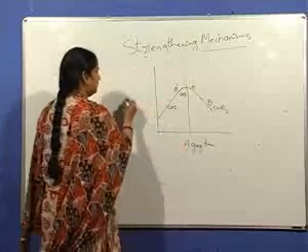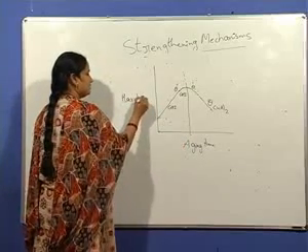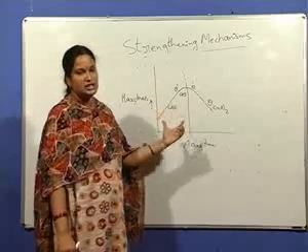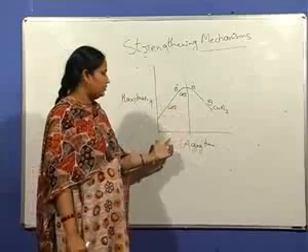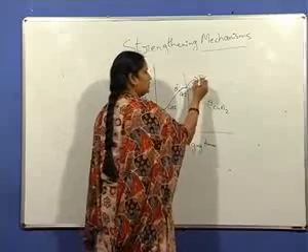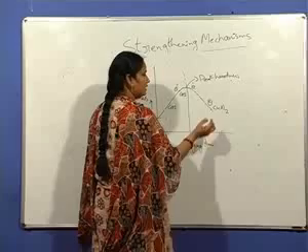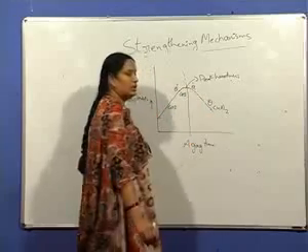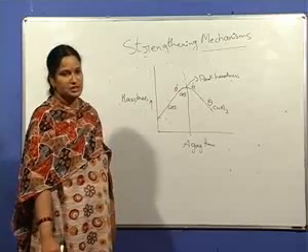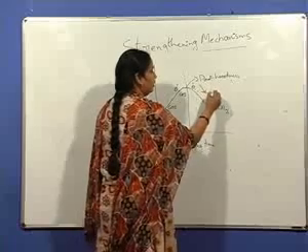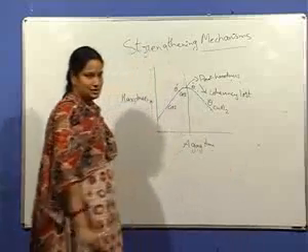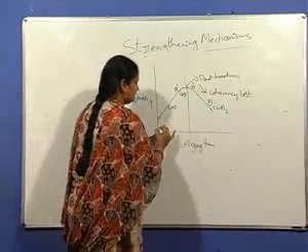And this is a plot between the hardness due to the various transition phases that occur during the aging of an aluminium copper alloy with respect to aging time. So peak hardness is achieved by the formation of theta prime, and still with increase in aging time, theta, the equilibrium phase CuAl2 forms from the transition phase theta prime. From here, the coherency is lost. The lattice matching is lost. The coherency is lost.